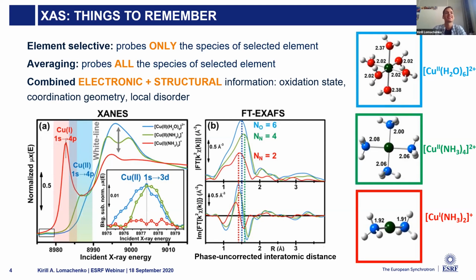You can see that the XANES spectra of these three compounds are very different, and each of the spectra contains features that are typical for a particular geometry and oxidation state. So that already gives an idea that XANES can be used as a fingerprinting method.